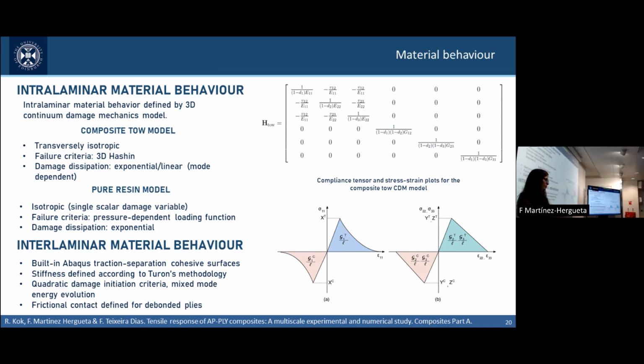We were talking before that we wanted to introduce the failure mechanisms as well. The failure mechanisms can be implemented using any single model that you would like to apply. Rutger tried thousands of them. These are the ones that gave us better stability for impact. So our intralaminar material behavior is included with two different models, a tow model and a pure resin model. The tow model is a transversely isotropic model, the conventional one, with a 3D Hashin failure criterion. It might not be the most accurate one, but what we found out is that it was quite stable. And that's why we finally went for this one.